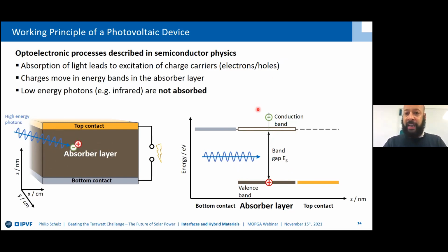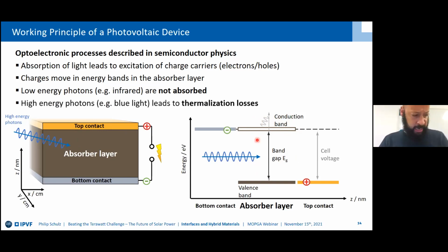This time we can excite electrons above the band gap, so they carry extra energy, but this extra energy is actually lost. They first thermalize to their relaxed state and then go to the terminals, which means you get more or less the same voltage, even though you get more input energy. This energy is lost due to thermalization that is happening extremely fast, and it's very hard to overcome this, but there will be some examples that I actually won't detail out too much.